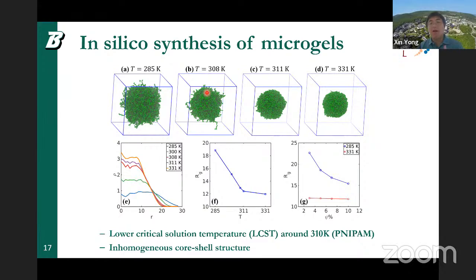and then we match that to the experiments. I apologize, I do not have a figure showing the phase transition. We have calibrated very carefully the phase transition curve, in terms of the polymer density as a function of the temperature, and we match the swollen density and collapsed density as well as the transition temperature. So that's one example of how we typically characterize that. And then the simulation units relate to those several physical quantities to determine the mapping between the DPD units and the physical units.